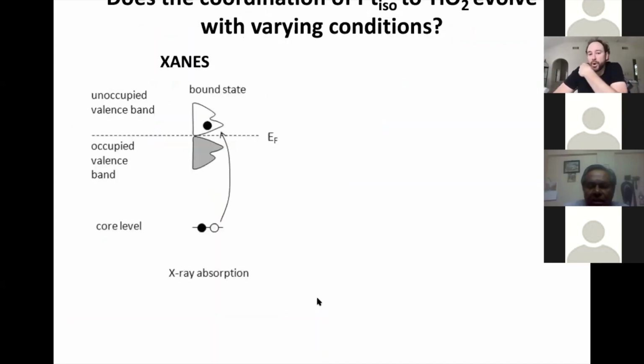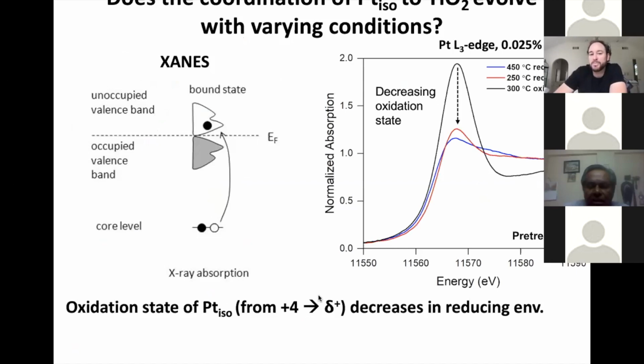So we can probe this using lots of different techniques. Here we've probed this using X-ray absorption spectroscopy. So XANES measures the transition from a core level state up to unpopulated valence states. And in this case, at the L3 edge, you're measuring mostly transitions into unpopulated D states. And so when you measure XANES, the absorption cross-section, basically how intense the absorption occurs at the platinum L3 edge, is related to the oxidation state of the metal. If the oxidation state is higher, you have a higher amount of unpopulated states, and so you'll get more absorption.